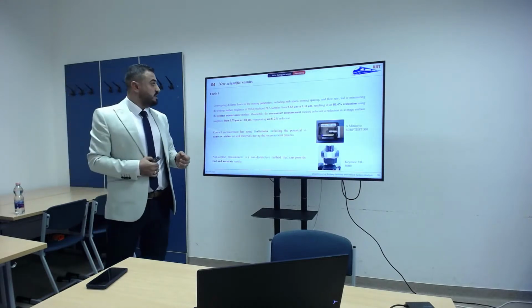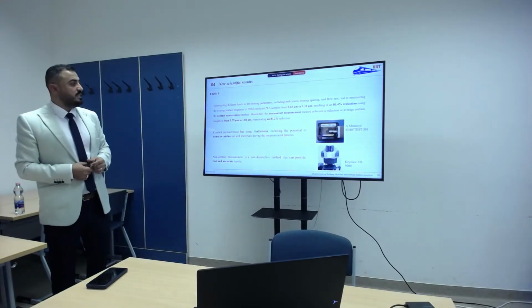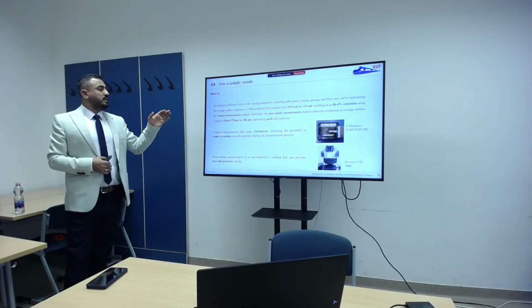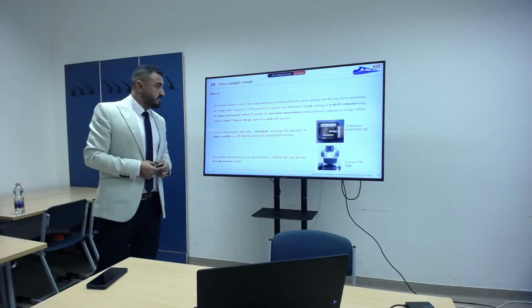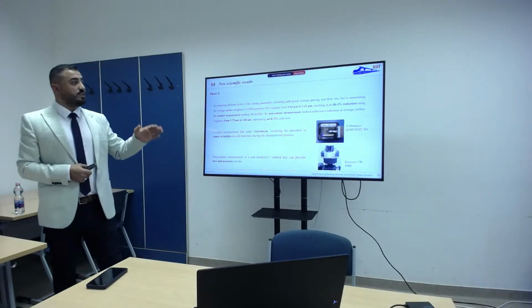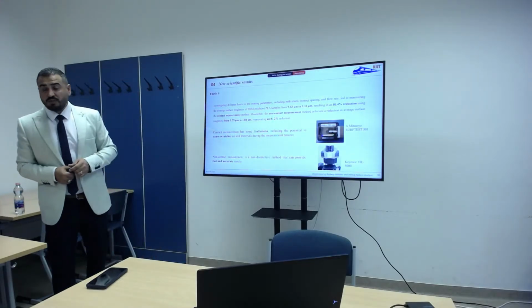So I investigated different levels of ironing parameters. With the investigation of all parameters and levels, I successfully minimized the average roughness from 9.63 micrometers to 1.31, about 86% reduction using the contact method, and with the non-contact method, about 81% reduction.